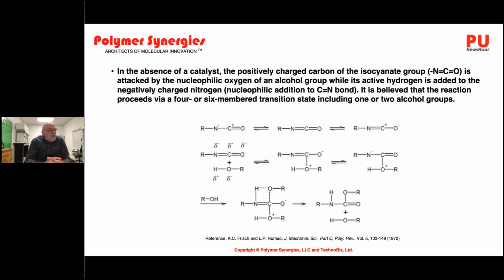And if we think about that chemistry a little bit more, in the absence of a catalyst, the positively charged carbon of the isocyanate in the NCO group is attacked by the nucleophilic oxygen, okay? And when we talk about nucleophiles, we're talking about things that donate free pairs of electrons. And so this particular reaction proceeds via a 4-membered ring to form our polyurethane product. This is still a matter of debate in polyurethane research, and there's a lot of work going on about how isocyanates actually react with polyols and other materials, certainly in the presence of different types of catalysts. So it's still an active area of research on the mechanistic perspective of how polyurethanes react.